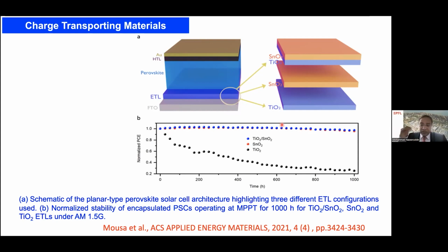By combining TiO2 followed by the tin oxide, that's the blue dots data. That shows this interface is very important. Pure TiO2 is not suitable. Either we have to use tin oxide, or a combination of TiO2 and tin oxide gives you the best performance, and you will find more details in this publication.